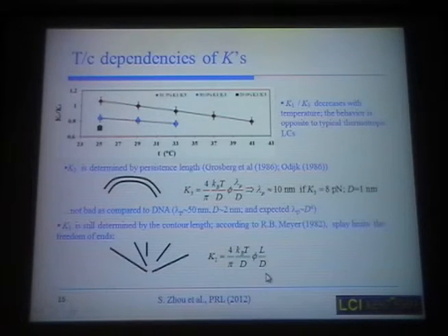And if you look at the literature of theories that consider elasticity of various dispersions in solvents, you will find that people associate the bend constant, which is deformation shown roughly here, with the so-called persistence length of the aggregates or molecules or polymer chains. And it makes sense. If the aggregates are very long or very short, it doesn't matter. What matters is how easy it is to bend each concrete molecule into this configuration shown over there.